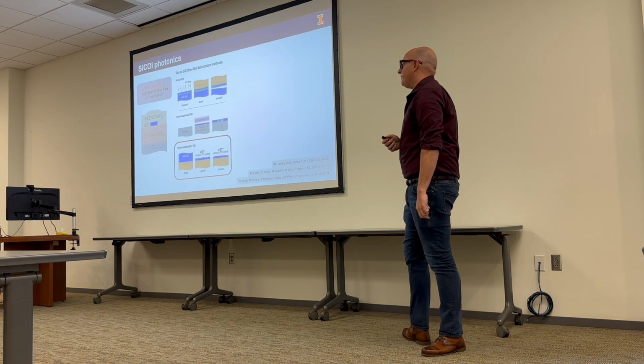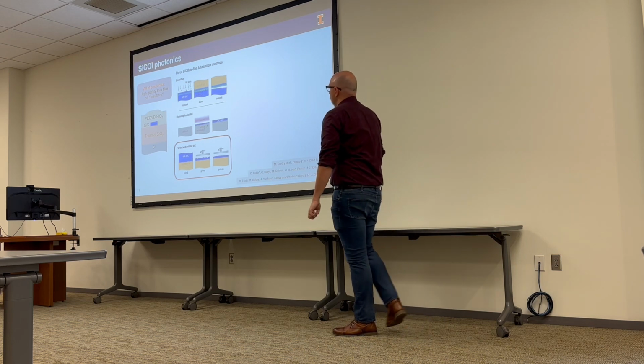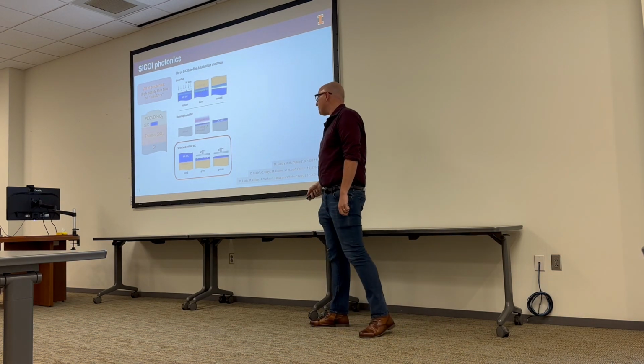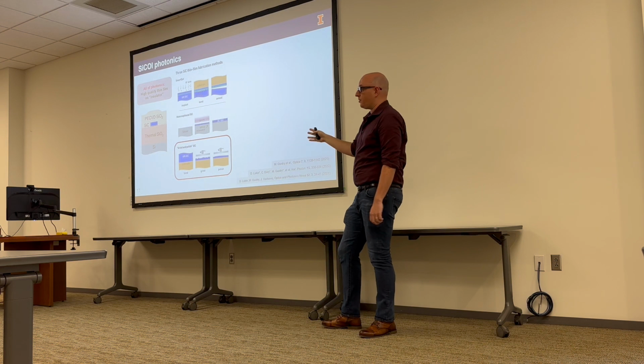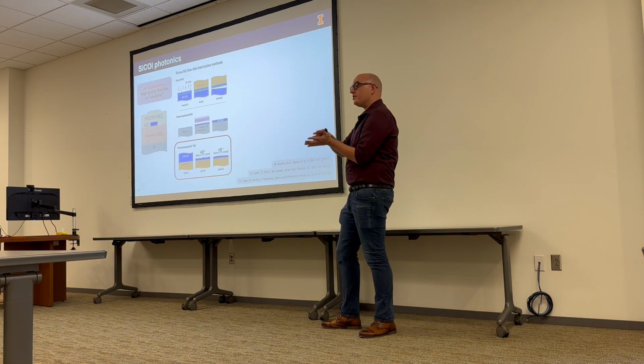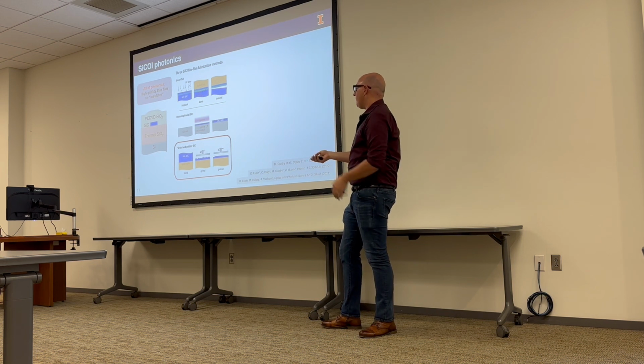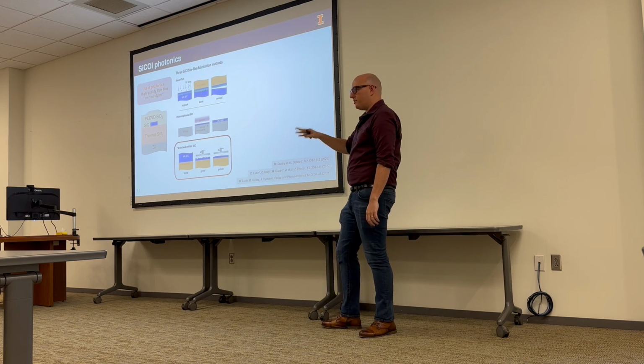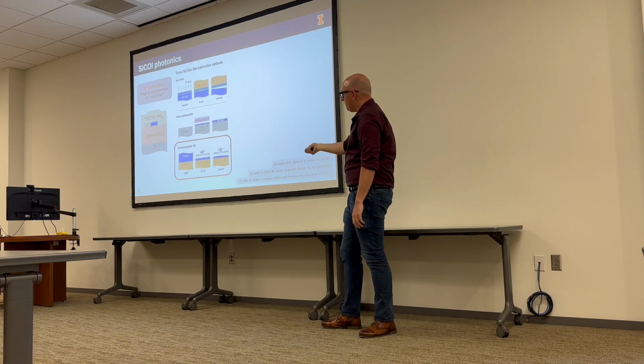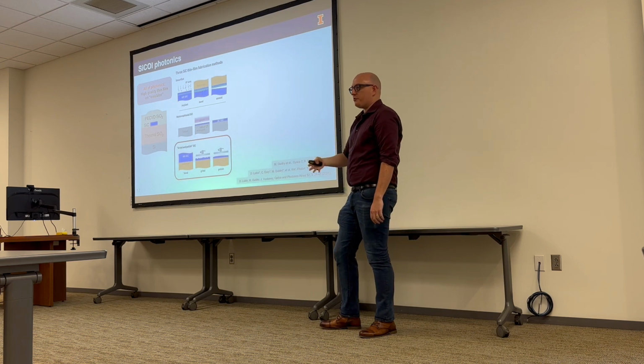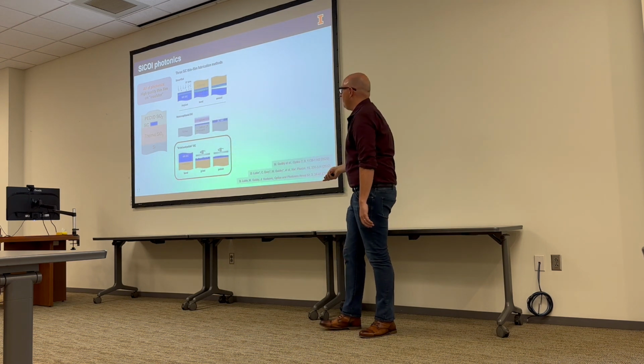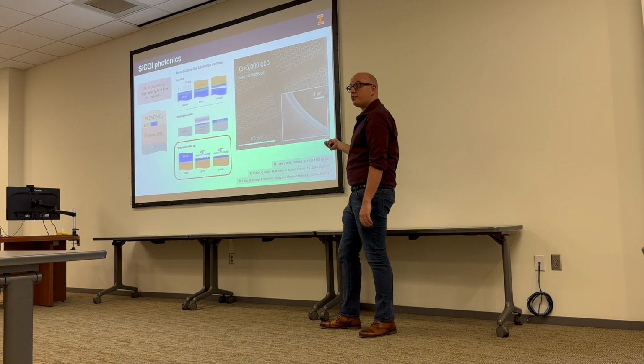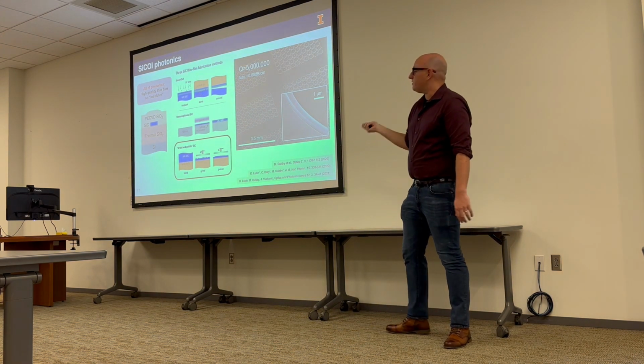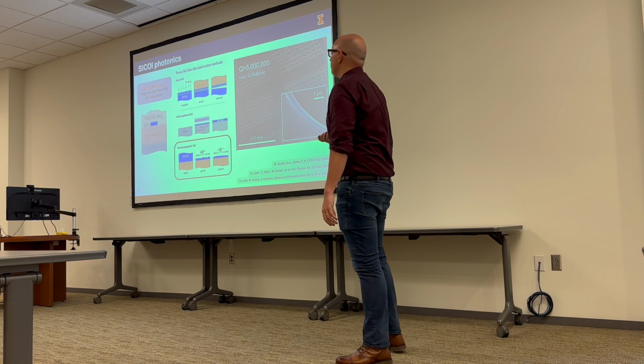The way that we make these thin films is very stupid. There's a few ways you can do it, but the way that we like is very stupid. We take this quantum grade silicon carbide, we bond it to either a silicon thermal oxide wafer or just glass. We stick them together, and then we take a grinding wheel, or basically sandpaper, and we mechanically remove 99.999% of the original material until we only have a micron film left. We go over with a CMP, we make it smooth and perfect. And then, once we have that film, we can etch it using very easy etching techniques into nice high quality factor optical resonators all on a chip.